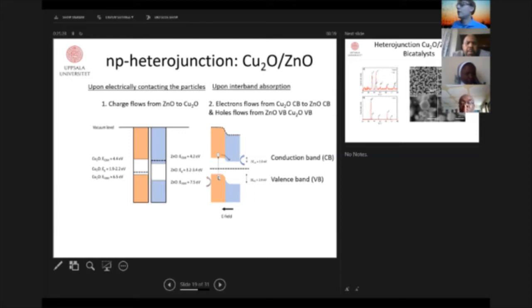So this is the semiconductor physics approach to separating electron hole pairs, which is used in many devices you find around us these days, from diodes to photodetectors and so on. The important thing here is actually the numbers. You need to place them so you're able to do the chemistry you want. For water cleaning purposes, you want the holes sufficiently deep to do the water cleaning, and if you have oxygen as a reducing agent, then you want this to straddle the oxygen levels. So there is some band alignment work to do. We did this for this system, copper oxide, which is a p-type, and zinc oxide, which is an n-type. And this is the scheme and the numbers for this system.